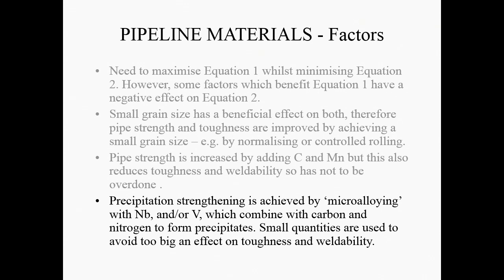So microalloying was developed by putting precipitation elements in that can combine with carbon and nitrogen to form little precipitates, which also increase strength. Again, if you put very small quantities of these elements in and have very small precipitates, it has a small effect on toughness and weldability, but a big effect on strength. If you put too much, then it's a problem. That's why we call it microalloying.